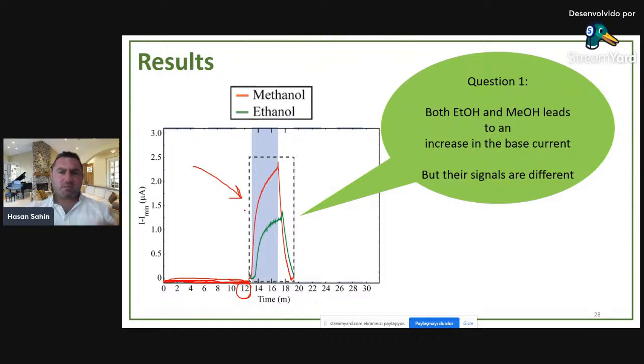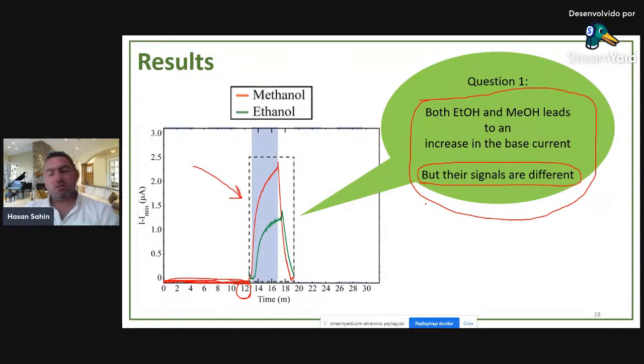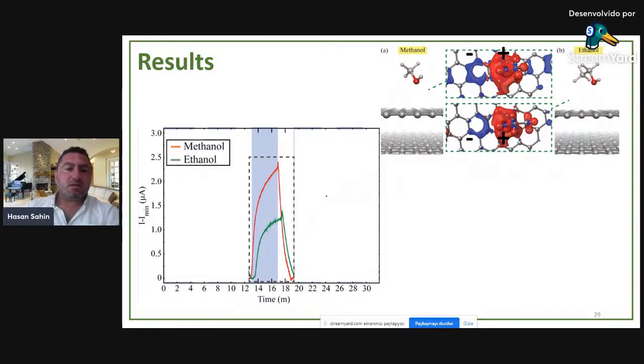Okay, so it seems that we are able to sense the organic molecules approaching towards the graphene surface. And question 1: both ethanol and methanol lead to an increase in the base current, and their signals are different. Okay, let's talk about it. What is the reason for the increase? If I perform some DFT calculations after experiments, we have graphene and methanol here, and again graphene and ethanol, from the top side view,